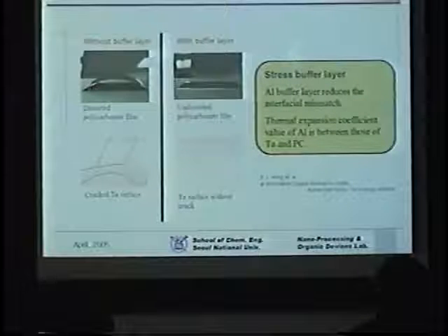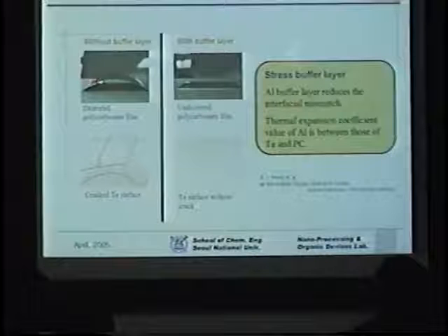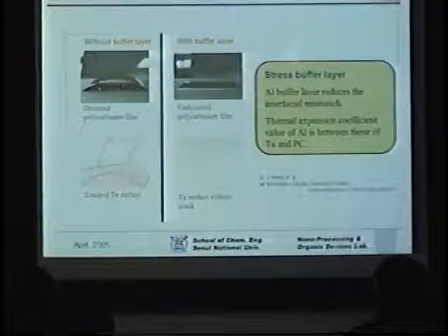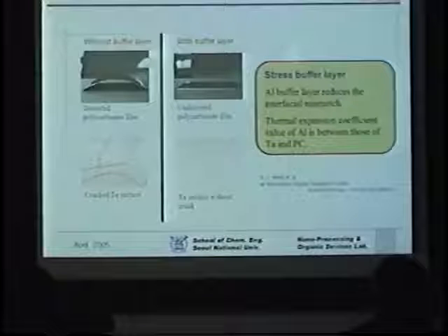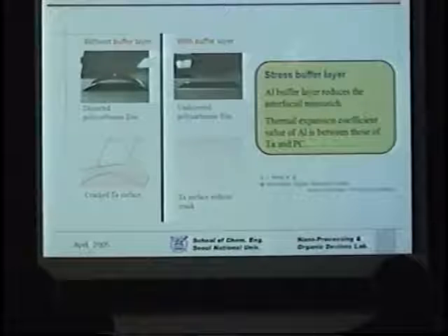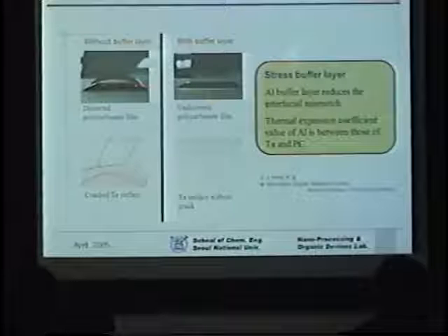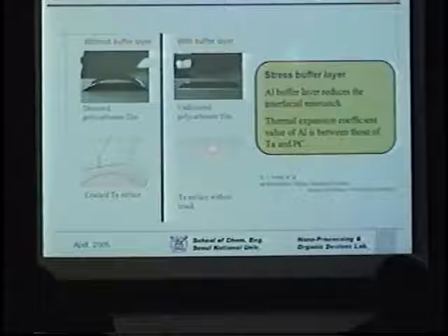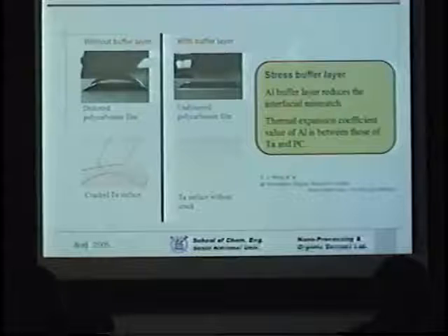Another example is given here. What we have here is a metal, Ta, deposited on a substrate. And as you can see, because of the difference in the thermal expansion coefficients, it bends. And of course, it can crack, that is, the metal surface cracks. But if you introduce an intermediate layer between the Ta metal and the polycarbonate film, you can see that the substrate does not bend, and you don't see any cracks occurring here. The reason is that you use aluminum between the Ta and PC, so that you can ease up the effect of the difference in the thermal expansion coefficients.